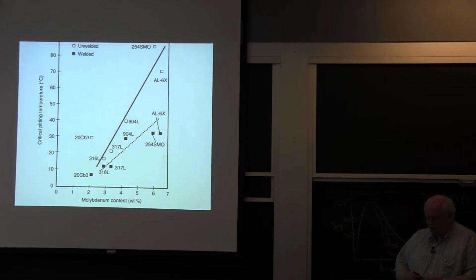I did leave something off before I went to nickel-based alloys. This is stainless steels and what's called critical pitting temperature. 316 stainless steel has a critical pitting temperature around 10 degrees centigrade, okay? And this is as a function of molybdenum content. 20 CB3 is a steel made by Carpenter Technologies. This is welded and unwelded, so 20 CB3 is 30 degrees unwelded.